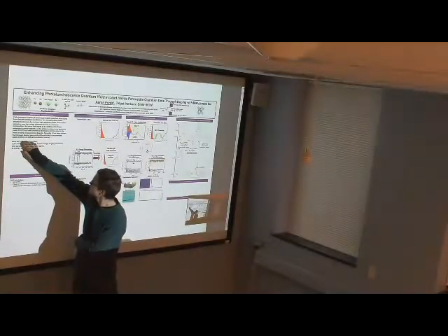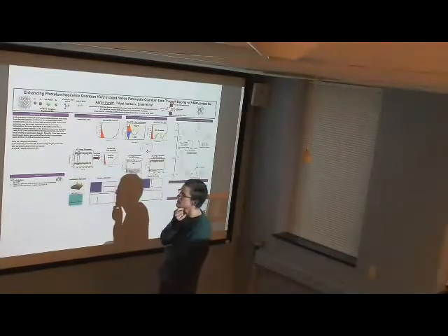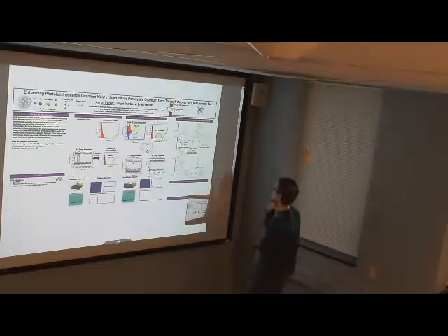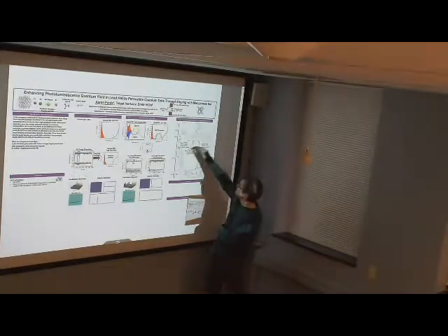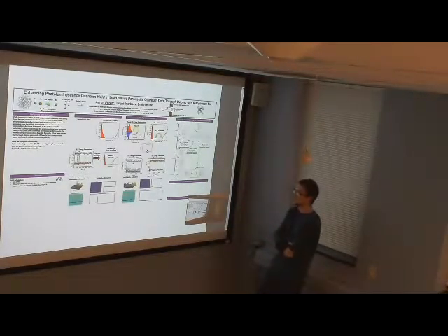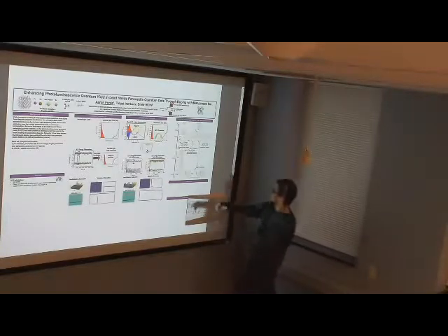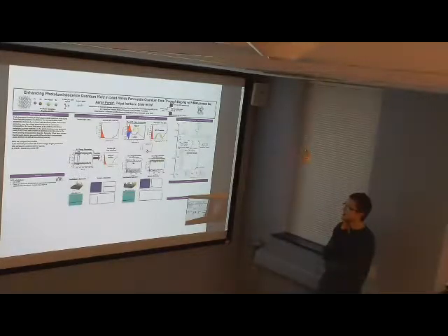Just knowing the experimental results, because I probably forgot to say in the introduction, experiment shows that the emission you get from these is about 600 nanometers, which is consistent with d-d transitions. If you look at just the band gaps, ligand to metal is like 3 eV and metal to ligand is like 2.4, so that would be more green. So yeah, it's widely hypothesized it's d-d transitions, so metal to metal.